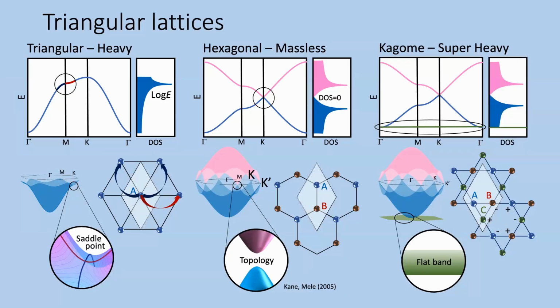Now, nothing really protects the flatness of the flat band in kagome lattices. So it's really the challenge of the crystal grower or material scientists to find kagome materials in which the flat band is as unperturbed as possible, because what we want to have at the end is a high density of states. The more it disperses, the less peaked the density of states is. And of course, to find materials at which the chemical potential is in the vicinity of this flat band.